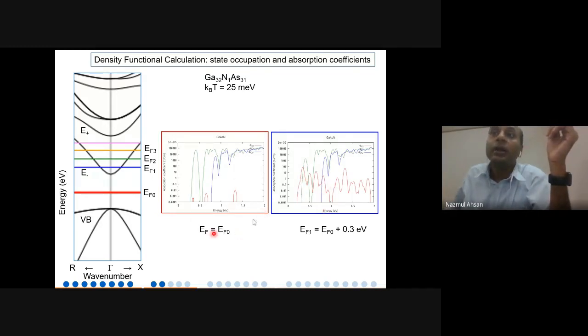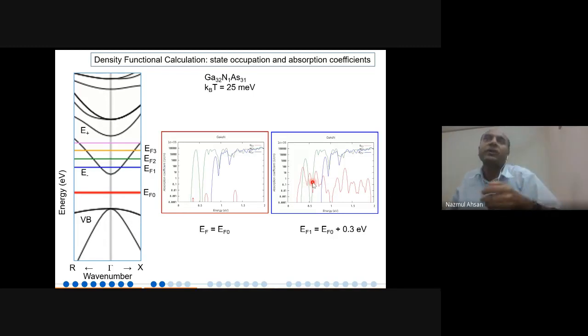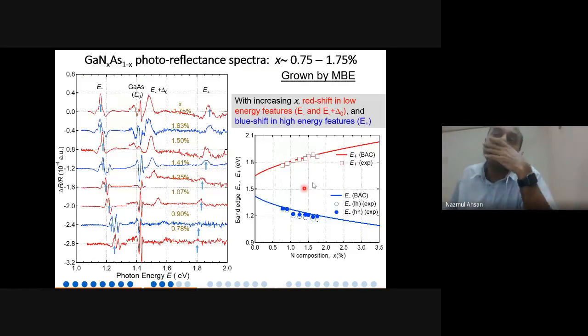So here your Fermi level is not well matched, but here you are shifting the Fermi level from the original position, and we are calculating the absorption coefficient, and we show that we can play with the absorption coefficient by first principle calculation. And this is the experiment